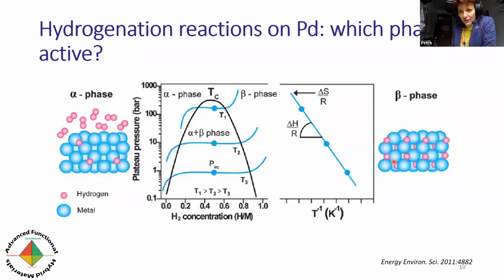Now, this is very important because once this phase forms, the properties of this material, this hydride, will be very different from the metal. So at the moment, I'm talking about the physical properties. For example, they're no longer metallic, so obviously the color would be different. They wouldn't be gray and shiny. And also the optoelectronic and electric properties would be different. So it would no longer be a conductor either. And this interstitial hydride for palladium forms at a relatively broad range of hydrogen pressures and temperature intervals as well. And that is important because obviously it also forms in the conditions that are industrially relevant for catalytic applications.